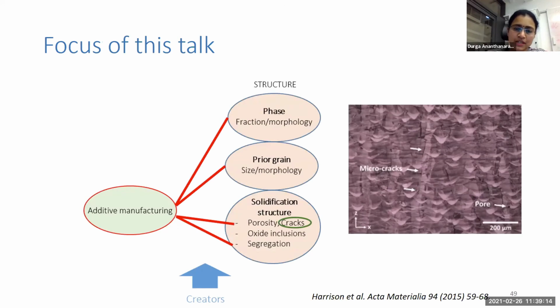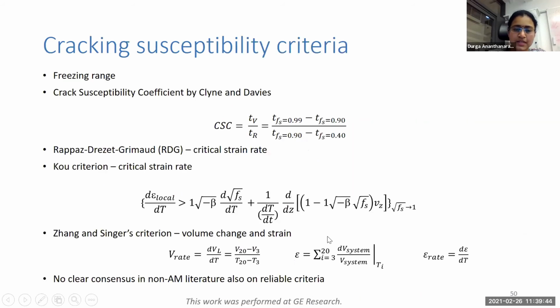So coming to the final part, which is on crack susceptibility. As I said, we have this type of grain structure and a lot of cracks forming if we don't optimize the conditions for AM. This is actually a result of everything that we saw so far. The solidification, the grain structure, the residual stresses, the segregation, all of this influences the crack susceptibility. Again, this is part of the work that was performed at GE Research.